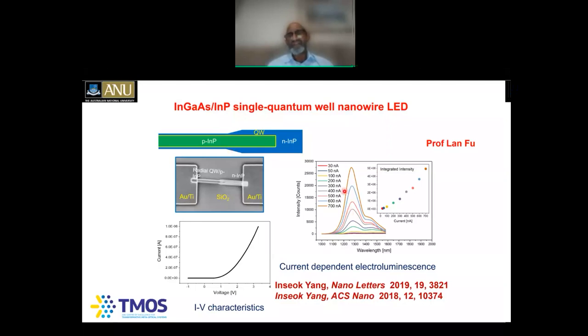And again, you can see that these are emitting in the 1.3, 1.55 micron window region, which I told you is very good for optical fiber communication applications also. But if you go and look at the light output versus injected current, you don't see any threshold-like behavior. You don't see any narrowing of the line width here. So essentially, it says that they're acting like a light-emitting diode, not like a laser.